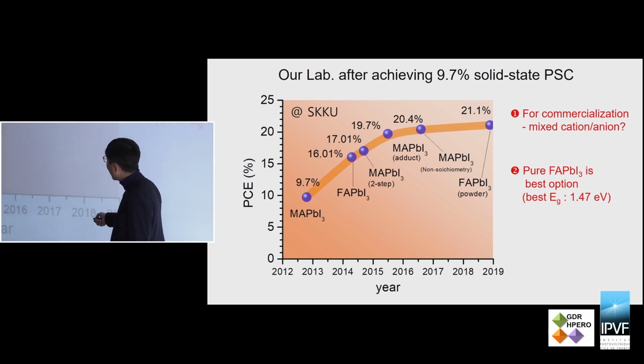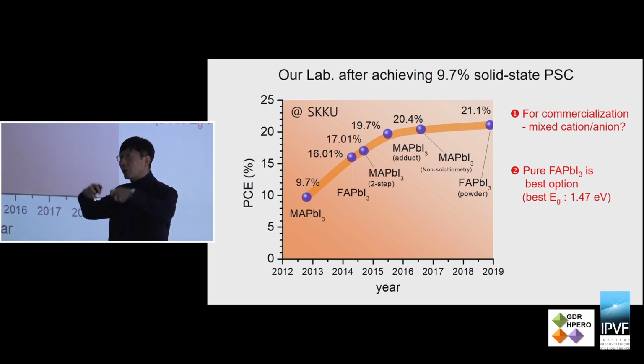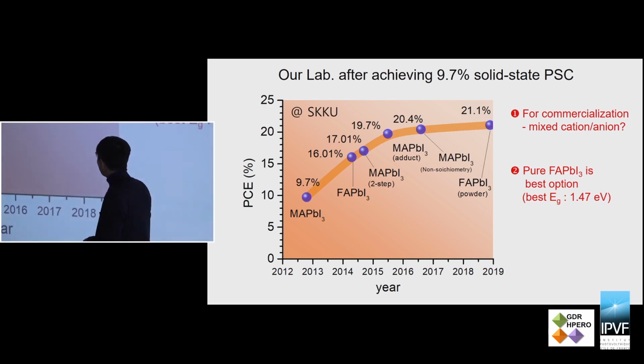Starting from 9.7% using MAPbI3, now we get 21.1%, which was certified, based on FAPbI3. Previously we used the precursor mixture as usual, but now we are using perovskite powder, inexpensive perovskite powder, and we can get high efficiency. So I will talk about this powder method in detail.